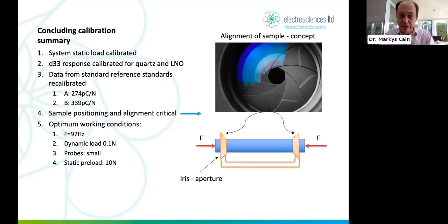We've calibrated the static preload. Good. We have a D33 response calibrated for quartz and lithium niobate. These are fairly standard, robust, solid materials. Sure, we can go to higher piezo coefficient materials. Might even go to single crystal materials, which are possible. Well, the relaxors, they're not actually that stable, are they? Anyway, we can use that quartz and lithium niobate to recalibrate the standard reference samples that come with the Berlincourt tool.